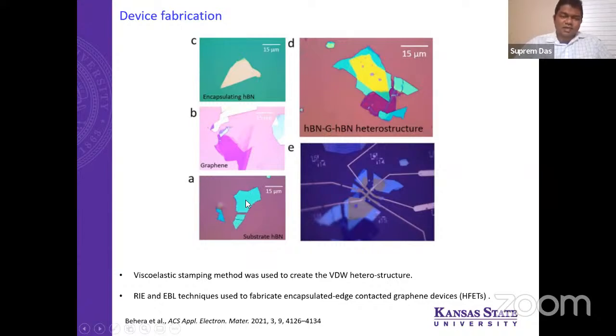You have a substrate, in this case hexagonal boron nitride, bottom layer. Then individually we have this graphene, and these are not very small. These are 10 to 15 microns, sometimes we get 30 to 40 microns, and then you have another hexagonal boron nitride. There is a technique, widely used now in various groups, and then you stack them together. This is the whole stack: hexagonal boron nitride, graphene, and hexagonal boron nitride. It takes some effort, but you'll be able to make it.